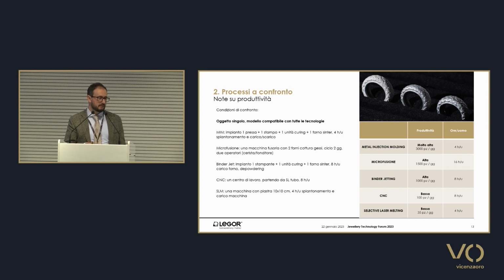The powdering also has to be included. In the case of CNC, starting from a semi-finished product, with 8 hours of work, only 100 pieces can be obtained, which is higher than what can be obtained with selective laser melting, but certainly it is a completely different order of magnitude if compared to binder jetting.